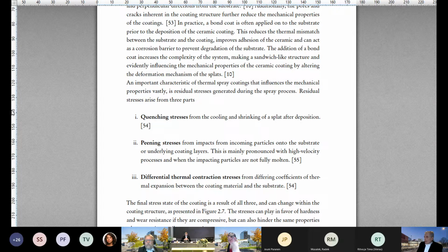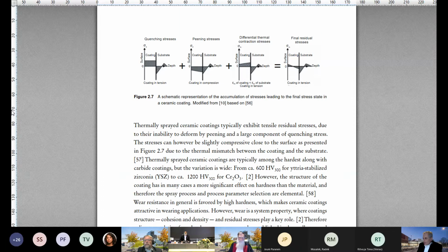But then can you describe the differences in the coatings? I think it's quite critical. Some of these coatings have tensile, or most of them are in tensile stress, but some of them are in compressive stress, which is, let's say, a big difference in the mechanical properties. Can you elucidate that in different materials using this figure that you showed? Yeah. Well, ceramic coatings generally would be in tension because of the lack of peening stresses. Plasma sprayed coatings almost always, I want to say. The compressive ones that I did find were HVOF sprayed coatings, and in these, I think